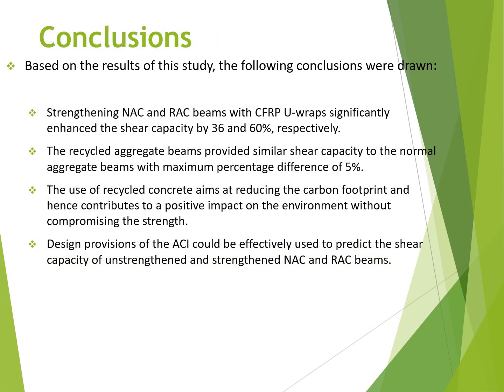In conclusion, based on the experimental results, the following conclusions were drawn. Strengthening of normal aggregate and recycled aggregate concrete beams with CFRP U-wrap significantly enhanced the shear capacity by 36 and 60%. In addition, the recycled aggregate beams provided similar shear capacity to the normal aggregate beams with a maximum percentage difference of 5%. The use of recycled aggregate concrete contributes to a positive impact on the environment without compromising the strength. And finally, design provisions of the ACI could be effectively used to predict the shear capacity of unstrengthened and strengthened normal aggregate and recycled aggregate beams.